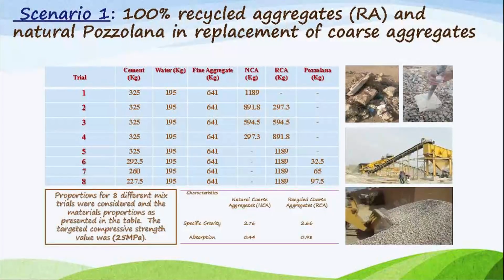If we compare the 8 scenarios at 7 and 28 days for compressive strength, the results show that 100% recycled aggregate and 10% pozzolana is the optimum result. We can use recycled aggregate in the concrete mix and add 10% replacement for cement. We have the optimum results. For the slump test or workability test for concrete, we also find the optimum result with 100% recycled aggregate and 10% pozzolana.